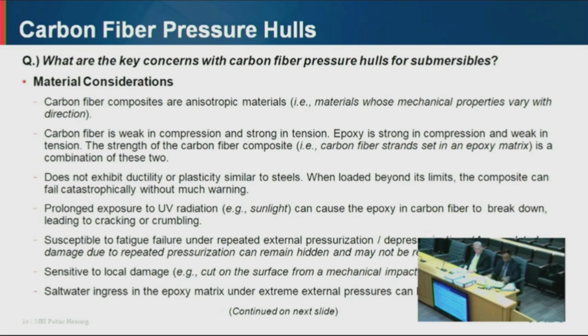Okay? So next thing is under extreme high pressure applications, carbon fiber composites are susceptible to fatigue damage under repeated external pressurization and depressurization. And the accumulated damage may remain hidden and may not show up. Okay? So the important thing here is unless the fatigue failure shows up as cracks or delamination, you really cannot see the damage. It may remain hidden in the carbon fiber strands. Okay? So once you have a crack or a delamination, the extreme high water pressures will accelerate the growth of the crack or the delamination. And the crack will grow very fast. Okay? And then you can have collapse or failure of the pressure hull.